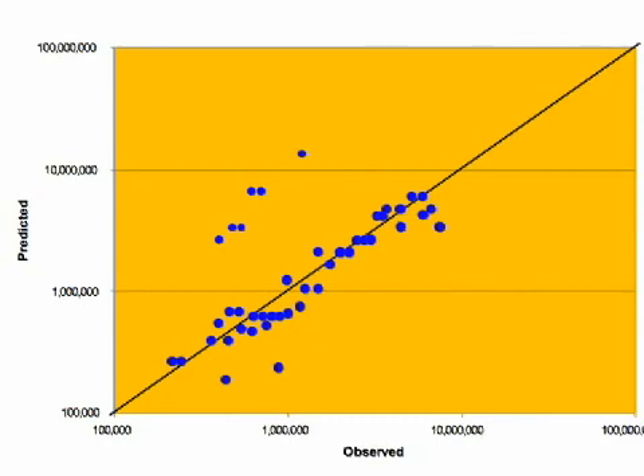Why don't we think that a new pavement is all cracked, make a pavement all cracked, and control the reflective cracking? Now, this is a new, different way of thinking. What we do so far is we control the stress on the top of the subgrade layer. We control the stress on the bottom of the asphalt layer, like the Asphalt Institute teaches us to do with the shell method. But if we have this material that is so good at resisting reflective cracking, why don't we control that stress? You'll see where I'm going with this.